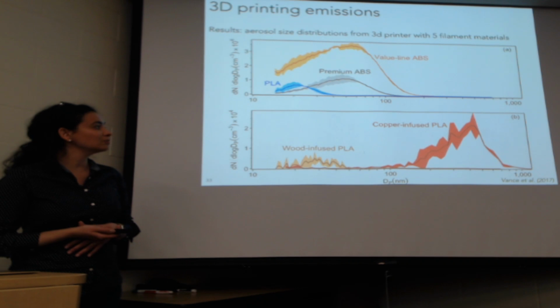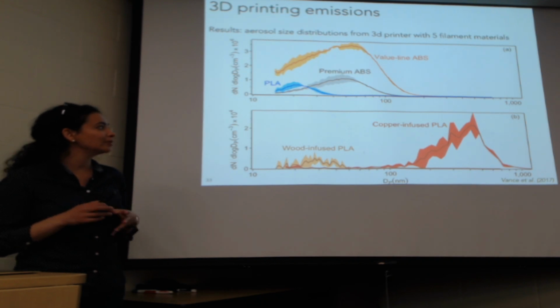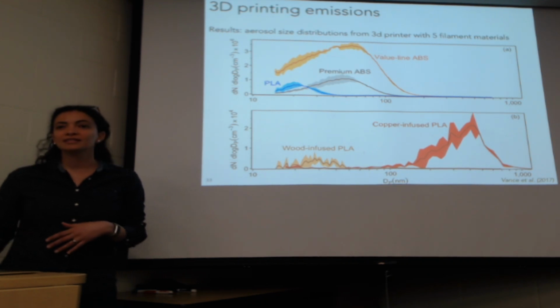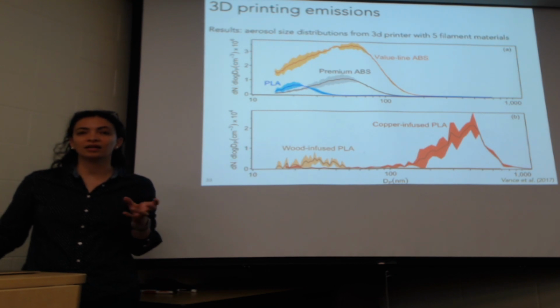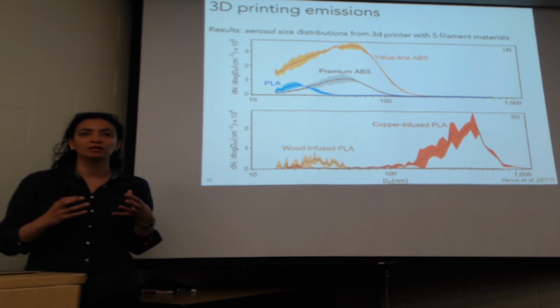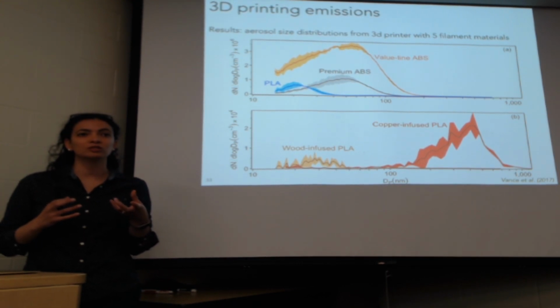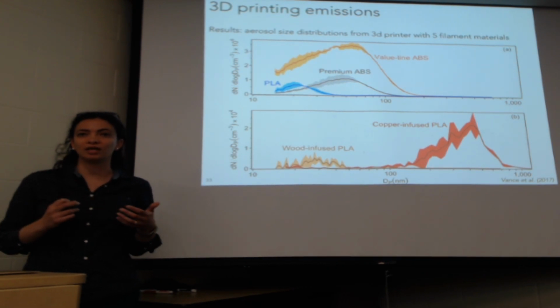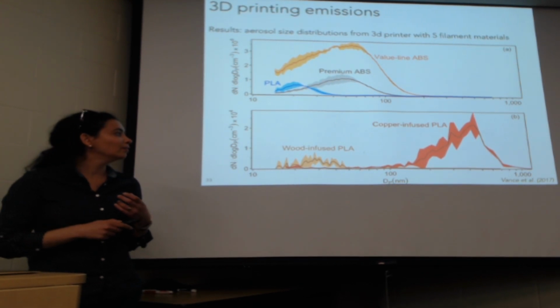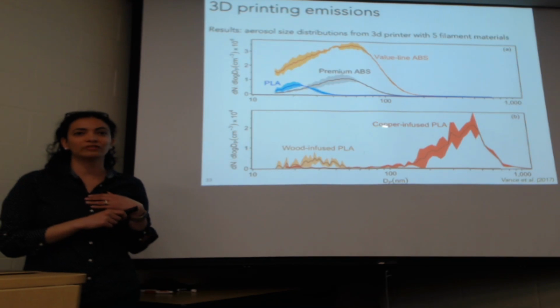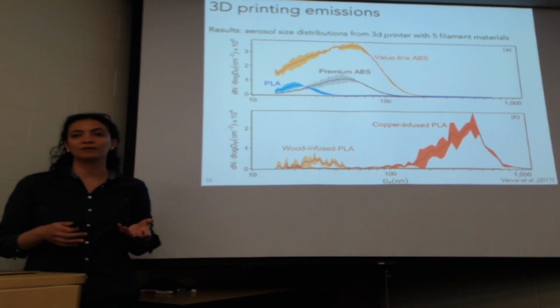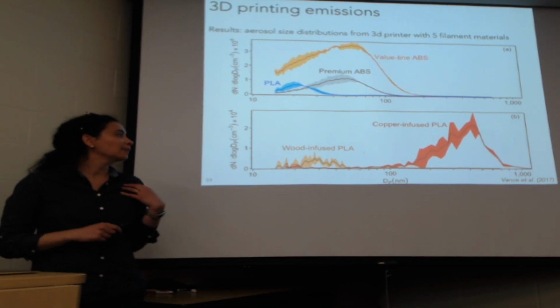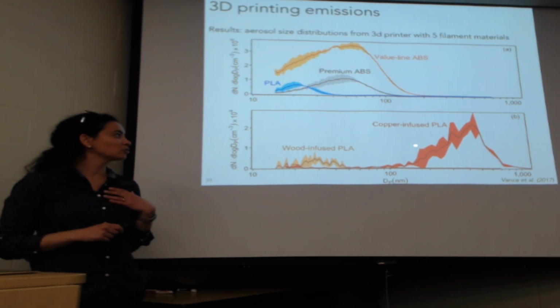We think something really interesting could be happening here, that the copper itself is acting as a catalyst, making particles grow and get bigger, which could be a really interesting solution to the problem. If we make the particles bigger, then they're less of a health concern. But at this point, like I said, this is all theory. What we know is that the copper printer consistently showed that particles were bigger.